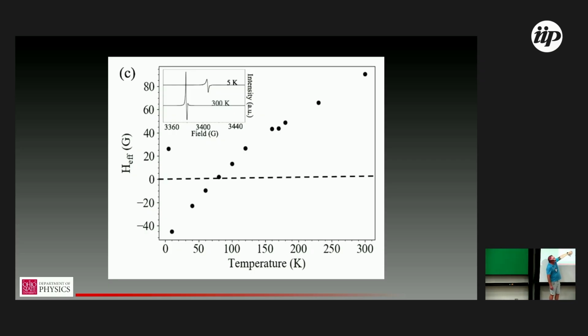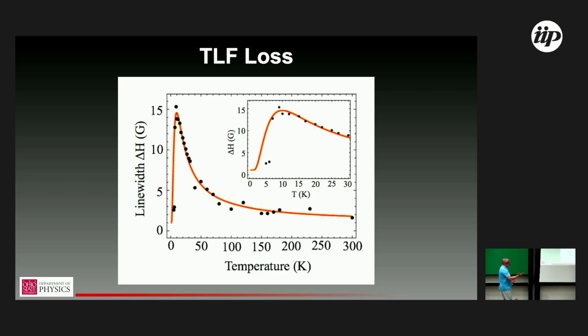So at very low temperatures, the anisotropy flips back. And this isn't like the sample cracking and peeling off the substrate or anything. This is all reproducible and traces back multiple samples, multiple scans. So we're left with a bit of a mystery that I'll let Greg solve in his discussion later on today, which is, what really is happening to the very low temperature damping of these systems. I think the fit above 10 Kelvin is good enough that clearly paramagnetic spins or two-level fluctuators are playing a large role here. But the very low temperature magnetism is, I think, complicated.